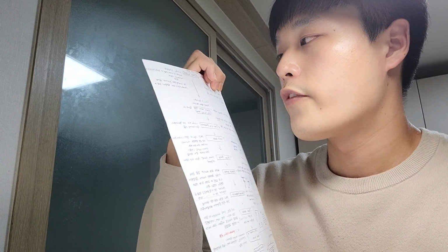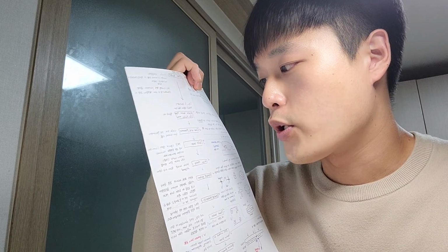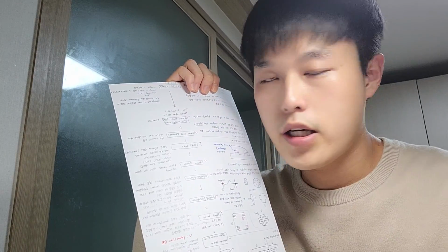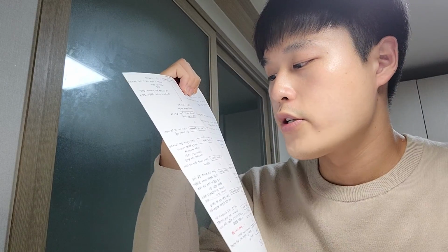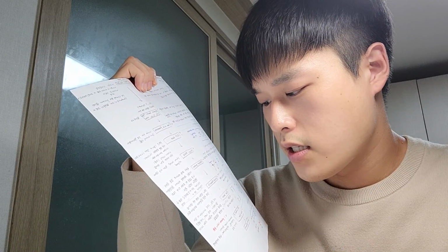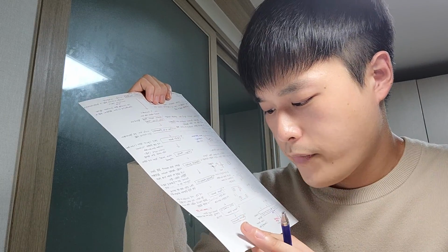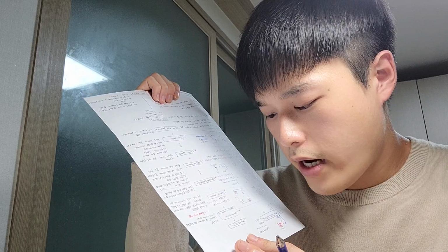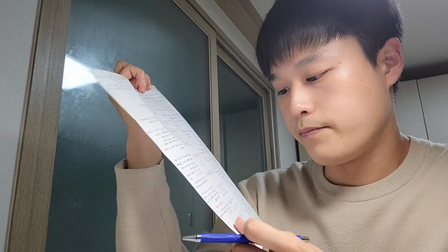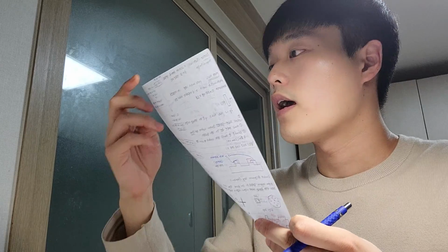First, clean the wafer and coat it with photoresist. After coating, we continue with soft bake, align the mask, expose the pattern, and develop the photoresist. Then one more bake, the hard bake, then etch the window in the barrier layer and remove the photoresist. This is the common photoresist order.